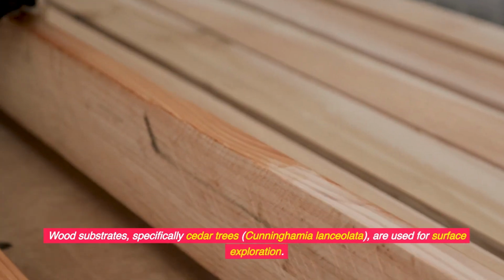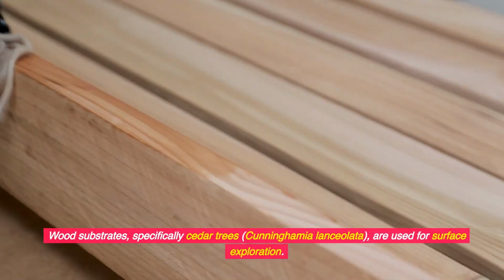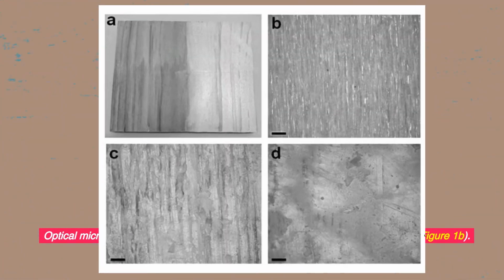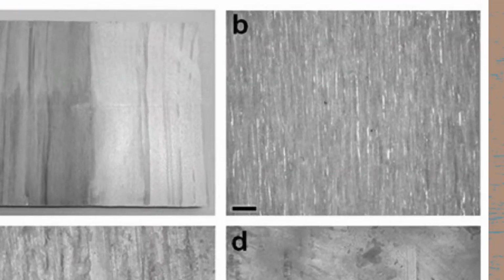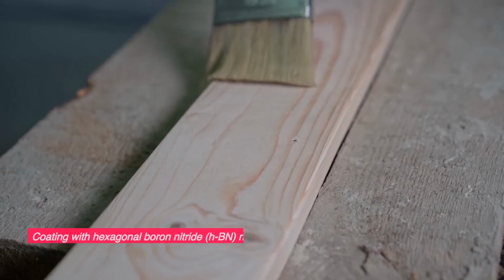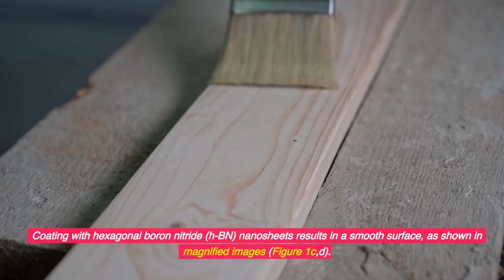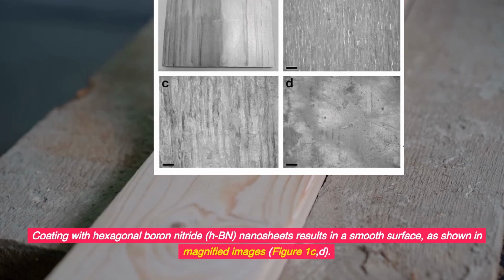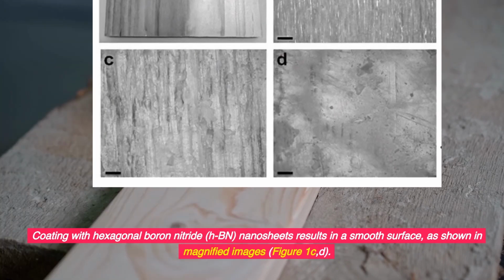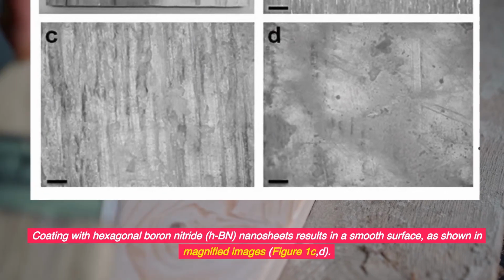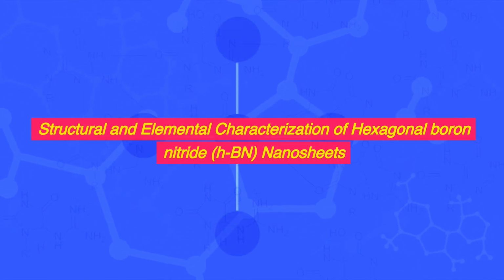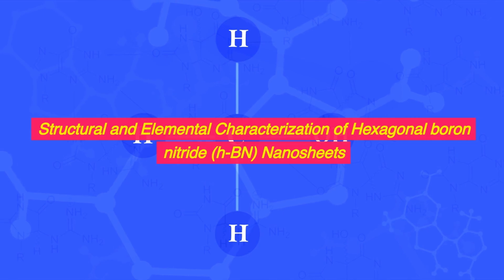Wood substrates, specifically cedar trees, Cunninghamia lanceolata, are used for surface exploration. Optical microscopy reveals a high degree of surface roughness in pristine wood, Figure 1b. Coating with hexagonal boron nitride, HBN, nanosheets results in a smooth surface as shown in magnified images, Figure 1c, d. Structural and elemental characterization of hexagonal boron nitride, HBN, nanosheets.